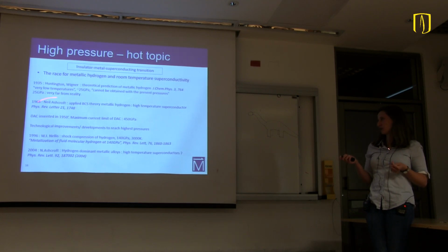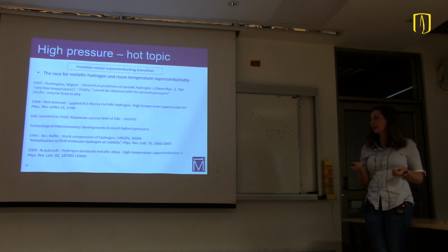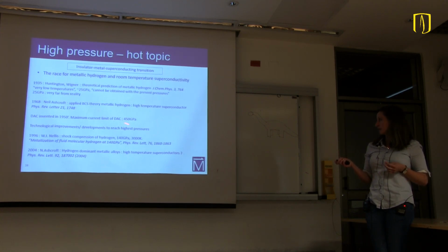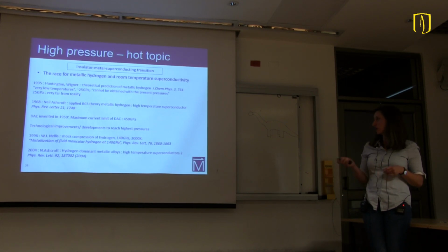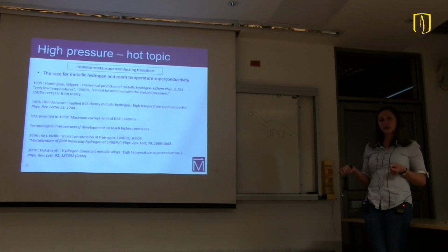Neil Ashcroft continued to push that effort, and that enabled huge technological improvements and developments to reach the highest pressures. Now the current limit for diamond anvil cells is 550 GPa, and this is massive pressure. Actually, metallic hydrogen was found in 1996, but for fluid, under shock compression, the other body of work for high pressure physics. But under those conditions, 140 GPa and really high temperatures, around 3000 Kelvin. That gave scientists an idea of what type of pressure to shoot for. But still, nothing was discovered.